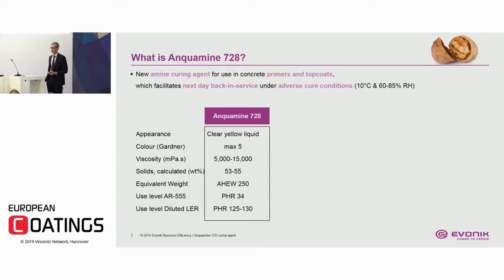In this case, what is special about this product is that you can cure it with solid epoxy resin dispersion, as well as with a standard diluted epoxy resin. So the AHEW, the equivalent weight, is 250. If you use it with a solid epoxy resin dispersion, such as the ANQUARES AR555, then we recommend the PHR 34. And if you use it with a diluted resin, you need a bit more material for obvious reasons, and you get a PHR of about 125.